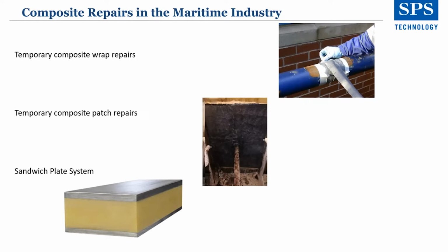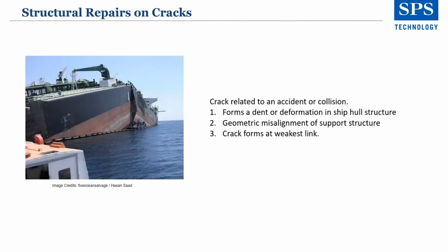And then we've got the sandwich plate system, which is a fully class-approved permanent repair, strengthening and upgrading solution that has been used on marine structures for over 20 years. With SPS, two metal plates are bonded by a polyurethane core. Now, the picture that I've shown on this slide, none of those three repairs will solve that issue. The crack related to an accident or a collision where it forms a dent or deformation in the ship's structure. There's a geometric misalignment of the support structure and a crack forms at the weakest link. Obviously, this is the worst case scenario.